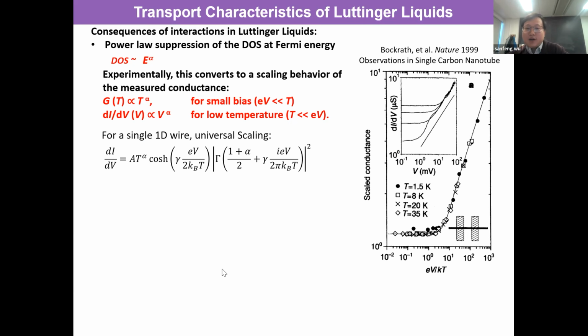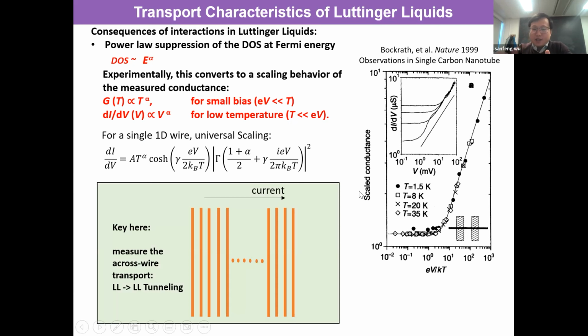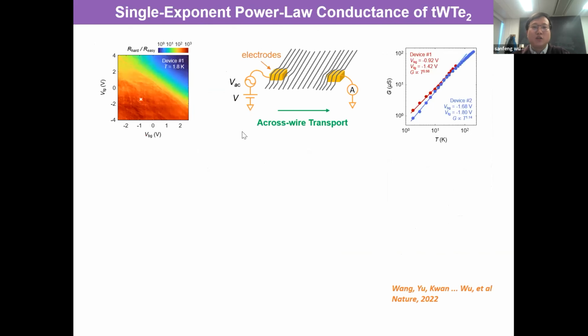That's something very similar to what we have measured, but in our case, we have a two-dimensional array of 1D wires. So the easiest geometry for us is to measure cross-wire conductance, just measuring along the hard direction. So you are actually thinking about tunneling between Luttinger liquids, right? So in that case, you should also see the power law suppression of the density of states. So that's what we're going to show here.